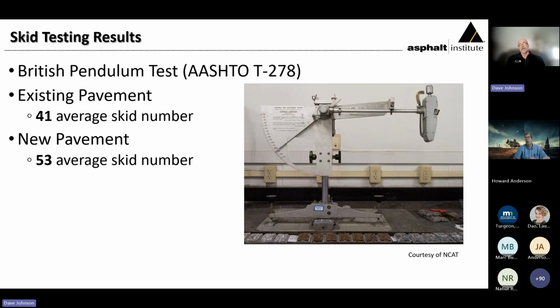Questions come up about safety, of course, and skid numbers at a truck weigh station. That's less of an issue than what we would have in terms of a more normal operation. But they did do some British pendulum testing of the existing material and then that new pavement, and notice that the values of that new pavement were very acceptable. Those values typically are going to go up a little bit in time as we remove some of the binder from that rock, and then they tend to stabilize. So 53 on that new pavement is very, very good.